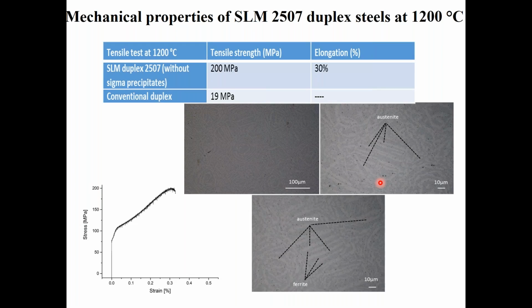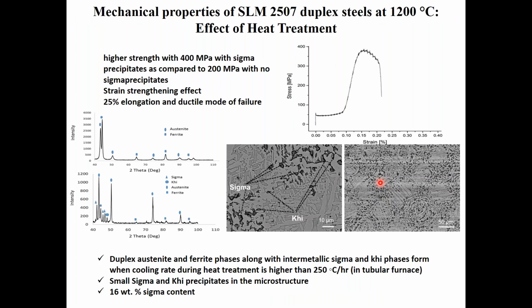Then we did the same heat treatment and tried to introduce the sigma precipitates, and conducted the mechanical test. We found very interesting results: the sigma and chi precipitates actually contribute towards high temperature mechanical strength. We got almost double the mechanical strength, 400 megapascal with sigma precipitates compared to 200 megapascal with no sigma precipitates, with 25% elongation, and the mode of failure was ductile. These are the XRD patterns of the two different samples, without and with sigma precipitates. So we were able to say that duplex stainless steel with sigma and chi phases in the microstructure, around 16 weight percent sigma content, can give better mechanical properties at high temperature, as high as 1200 degrees centigrade.